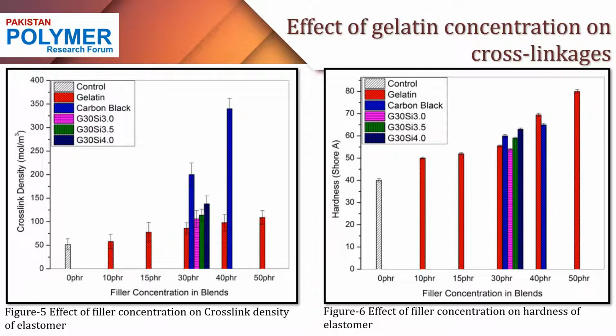As you can see, with increasing concentration of gelatin, the cross-link density goes on increasing in a constant way. This is because the increasing concentration of gelatin reduces the absorption of solvent within the intermolecular chains of the elastomer. This reduction in solvency or swelling causes an increase in cross-link density or percentage cross-linking of the elastomer. Along with this, you can see that with the incorporation of silanized silica at constant phr of gelatin, the cross-link density increases further from 100 to 150. This might be because silanized silica aids in the formation of crosslinks in the elastomer. Irrespective of that, the carbon black possesses the highest cross-link density of 300 to 350 moles per meter cube. Gelatin possesses an increasing trend in the cross-link density.